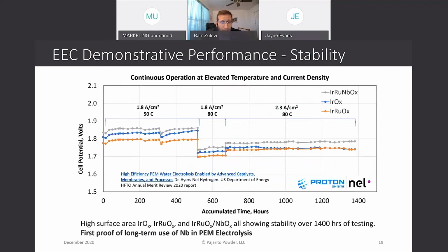But more importantly, a 1,400-hour test of these materials under different operating conditions, including 2.3 amps per square centimeter at 80 degrees C for nearly 800 hours, shows stability. This is extremely exciting because this is the first demonstration in an actual cell of long-term niobium. And this really opens up the door for including niobium as a platinum reducer. So again, we're seeing the same performance compared to the baseline effectively, but at a 40% reduction in iridium, which is a great improvement.